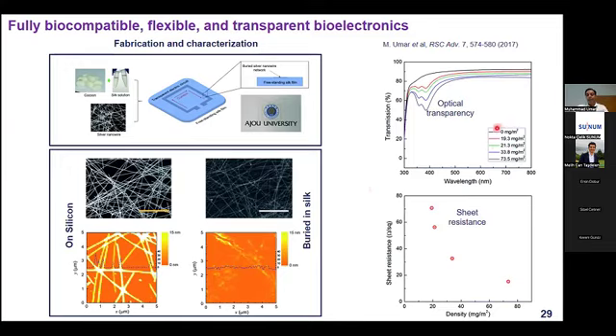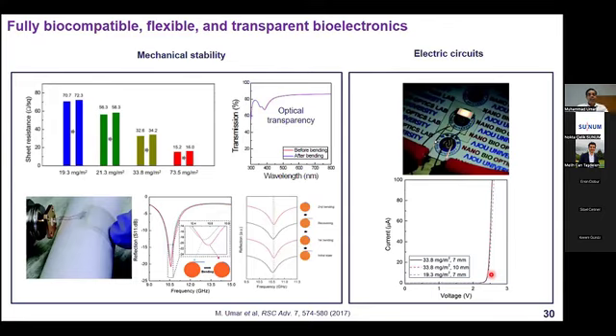So here we showed that by changing the concentration or amount of silver nanowire, if we increase the amount of silver nanowire, optical transparency slightly reduces, but we can decrease the sheet resistance. This sheet resistance is similar to ITO, because many electronic devices, wearable electronic devices, are based on ITO. ITO is very expensive. So this silk plus silver nanowire could be a good replacement for ITO-based devices. And then after basic characterization, we also check the mechanical stability.